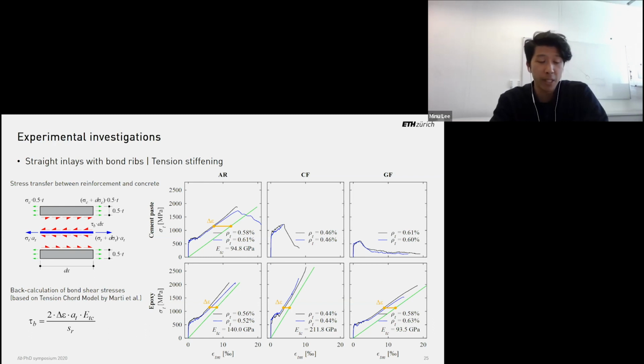And in the rovings with epoxy, where it really was possible to go into the full cross-section of the roving, we believe that the stress distribution within the roving was much more homogeneous, and therefore higher stresses could be reached, and foremost also higher elasticity moduli. Unfortunately, we only have one direct comparison between the cement paste and the epoxy here on the left side with the aramid fibers, because the other ones failed already after cracking. And we can see that we actually reach a much higher elasticity modulus for the epoxy coated fibers than with the cement paste coated fibers.